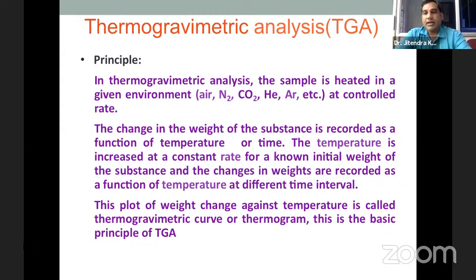But those can also be used, but lower than 1000 degrees centigrade. For a particular application, when you decide on the area where you want to work, the thermal stability of that particular composite, coating, or compound is very important. Here, with respect to temperature, you can obtain the weight loss. This weight loss according to the temperature gives you the thermograph.